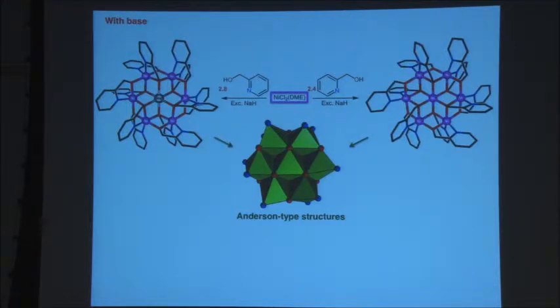If you have here slightly more ligand to metal ratio, the central position is occupied by the sodium cation. Instead of divalent nickel 2, you have monovalent sodium 1. So you can selectively incorporate now the sodium in the center of the wheel. That, of course, again, for catalysis is very important to know. If you look at the structural motif, and if you take here this three-dimensional polyhedral view that is often used in solid-state chemistry or in coordination chemistry, you see here the octahedra sharing edges.